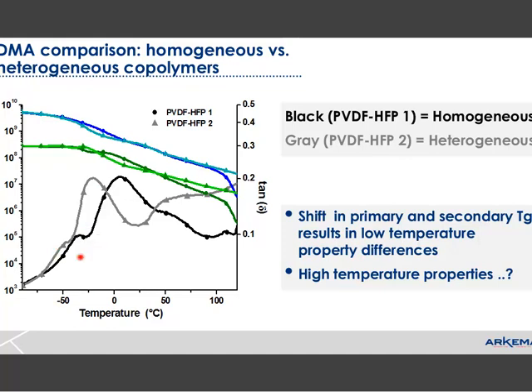The low temperature T sub G, I'll point this out, usually controls slower processes such as low temperature mandrel wrap, and usually that would be an indication that these products would perform very well down to -50 degrees C for those sort of tests.